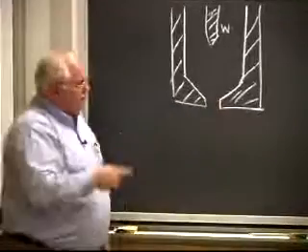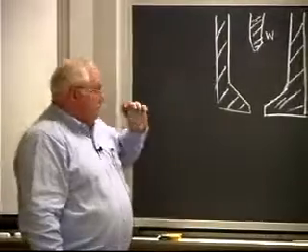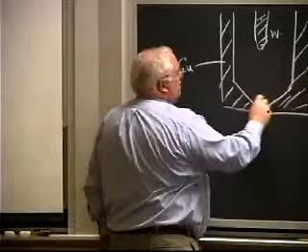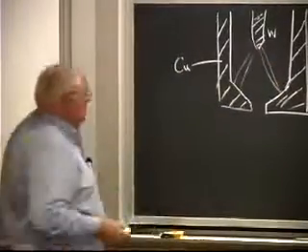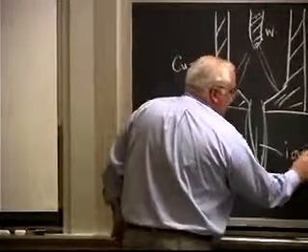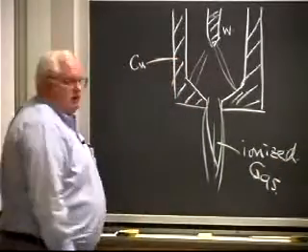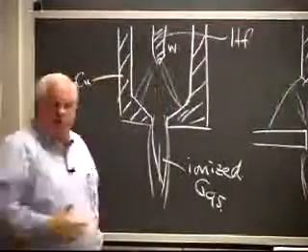Well, it turns out that from that little observation, Union Carbide in the late 50s invented the plasma arc welding process, where you have a tungsten electrode and a water-cooled copper shell, and you basically strike an arc inside a chamber at constant volume, and you have a gas jet, in this case an ionized gas, which originally was argon, but people have learned to use other things. Rather than tungsten, they now use hafnium as the electrode, which is also a refractory metal.